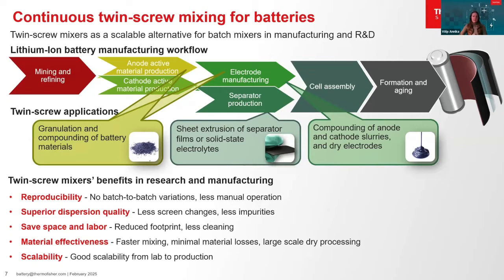Material effectiveness is enhanced. The mixing process is significantly faster with twin screw mixers, completing the task in minutes rather than hours. Continuous processing then minimizes the material losses, making the process more efficient. Twin screw mixers are also effective for large-scale dry processing, which we talk about later. Twin screw mixers provide good scalability due to the large surface-to-volume ratio in the mixer, making it easy to transition from lab-scale experiments to full production. High material and time consumption in manufacturing scale create the need for lab-scale twin screw mixers for advancing battery R&D. A downscaled solution is presented now on the following slide.